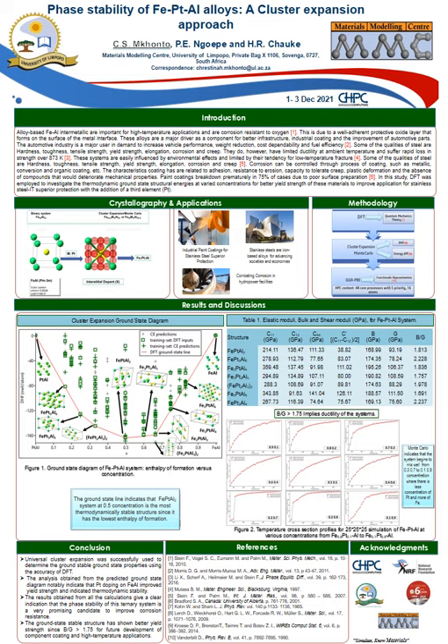We further use Monte Carlo to determine at which concentration the material begins to mix well. We note that at 0.3 concentration of platinum and 0.7 concentration of iron, the structure begins to show proper mixing at 1,300 Kelvin, clearly indicating a phase change. Up until 0.1 concentration of platinum and 0.9 concentration of iron, a phase change occurs at about 1,800 Kelvin. This indicates that the material can be a promising candidate for high-temperature applications.